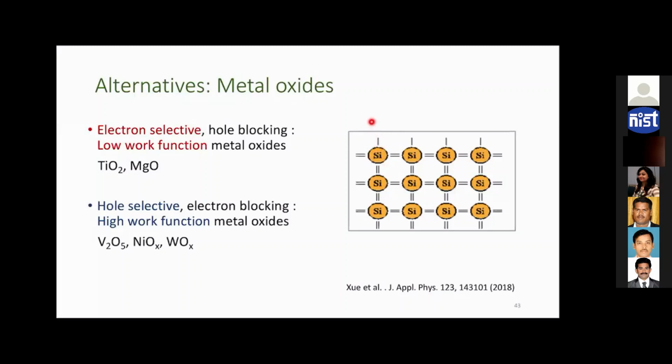Because if they are sitting exactly on top of the crystalline silicon and these atoms are coming from a crystalline material, then the atoms that you are using to passivate the crystalline silicon surface bonds, if they are crystalline, have a certain periodic arrangement which is different from the arrangement of the crystalline silicon. The mismatch between the periodic arrangements will create a strain in these surface bonds, making the bond vulnerable to break.